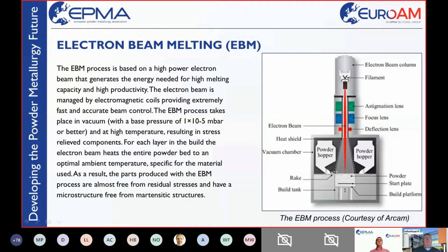Another special thing with EBM is that every powder layer is preheated before it's melted. This preheating results in a hot process compared to laser melting. The big advantage of EBM, therefore, is that we have very, very low or almost freedom from residual stresses. Therefore, EBM is used for very special materials and has found its way into the market next to the laser beam variant of more or less the same powder bed based process.